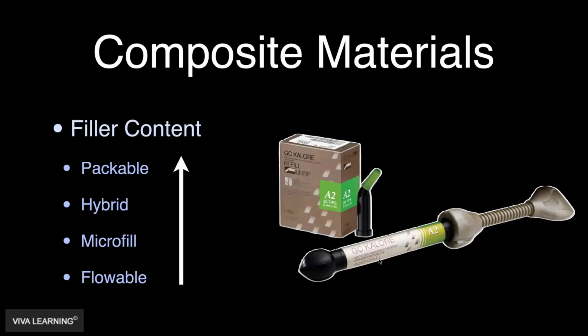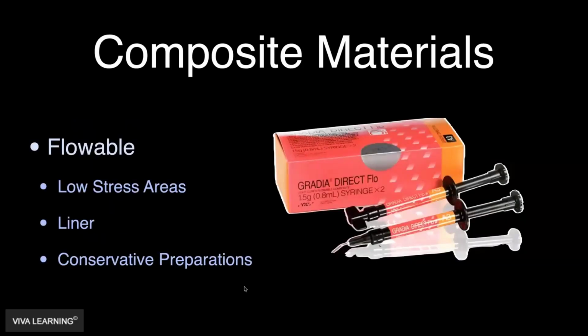And all those different filler percentage flowables, it was still flowable, and it still basically all had the same clinical indications. None of those materials had wear rates that allowed them to be the surface layer on a functional surface of a tooth. So occlusal table in a class 1 or class 2, lingual in a class 3 or class 4. They just didn't have the physical properties because the filler percentage was not high enough that we would cross that threshold, right? And so even in the world of high filler percentage flowables, we were still using them in really low stress areas, non-occlusal or functional areas, kind of as a liner underneath other composites. Some of you may have used them in something called the snow plow technique, where you would put flowable in a class 2 box, leave it uncured, then pack material on top of it to try to get it to seal your margins.